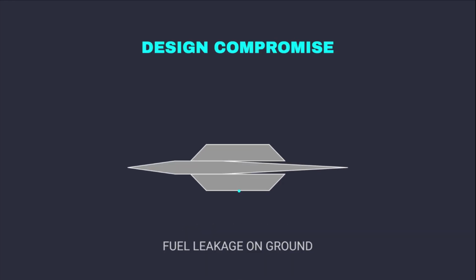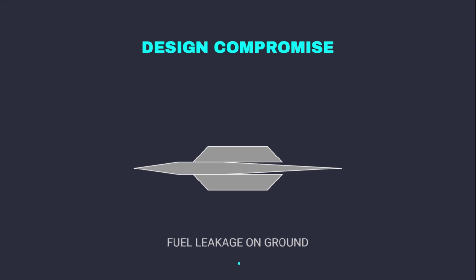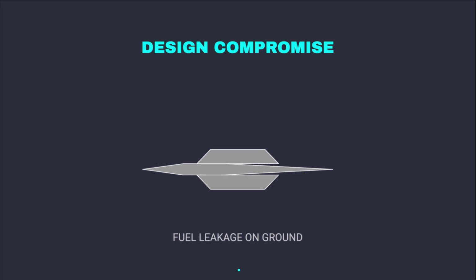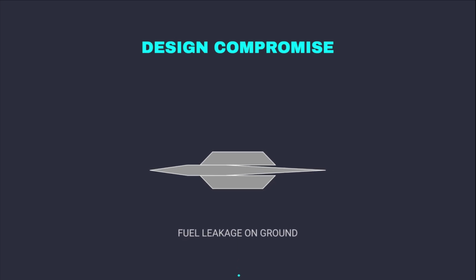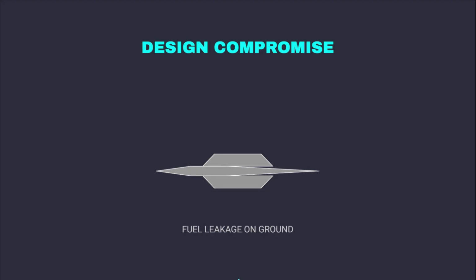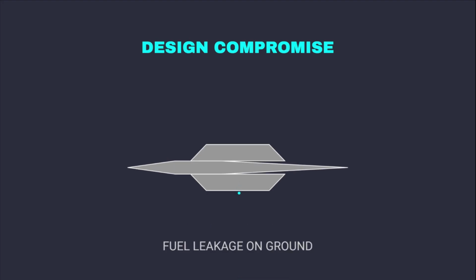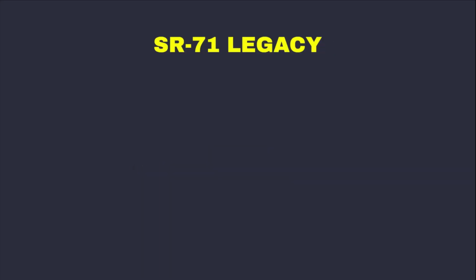The final assembly of the SR-71 required specialized tooling designed to handle the unique properties of titanium. Because titanium is prone to galling, standard fasteners could not be used. Specialized titanium fasteners, often silver-plated to prevent cold welding and seizing, were mandatory for all structural joints. Furthermore, the airframe was designed with intentional gaps and loose panels. These tolerances accounted for the massive thermal expansion that occurred during high-speed flight. The aircraft was structurally sound only when heated to operational temperatures, meaning it leaked fuel profusely while stationary on the ground, a necessary design compromise dictated by the material science.